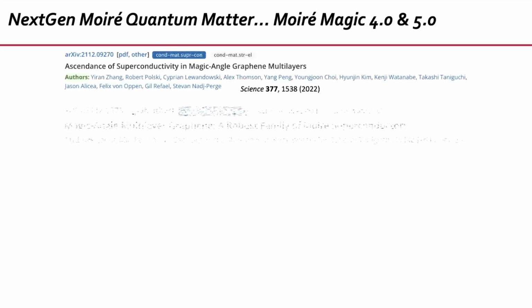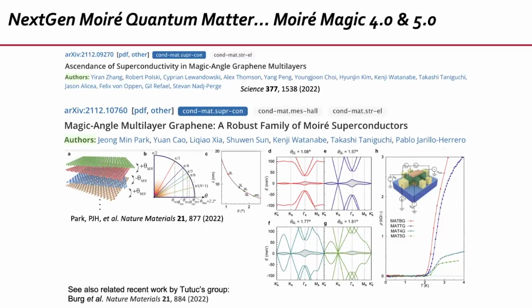And the following year, again, several groups, as you can see, the group of Stefan Nadj-Perge and my group, we published about superconductivity in magic angle twisted tetra and pentalayer graphene. And the group of Emmanuel Tutuc, who's here, published also very interesting results on correlated physics on these 4 and 5 layer systems. As you can see, again, these papers appear in multiples of 2 or 3 by different groups. So it makes a very convincing case very rapidly for people to look at their properties.